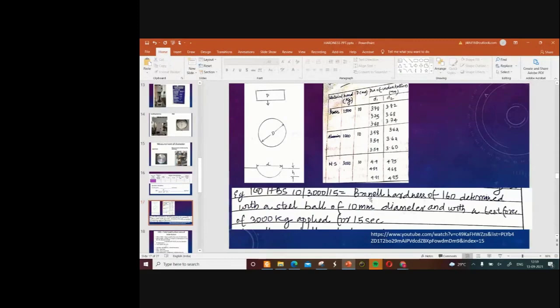This means that a Brinell hardness value of 160 is determined with a steel ball of 10 mm diameter, as you see here, 10 mm diameter, and with a test force of 3000 kilograms. So this corresponds to this mild steel, 3000 kilogram, and it is applied for 15 seconds. So how much time the static load is applied, it will be the last number. So clearly 160 is the hardness value, 10 is diameter of the indenter, then load, and time of application.